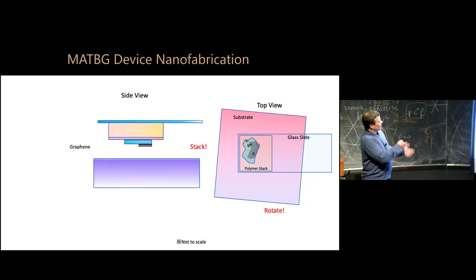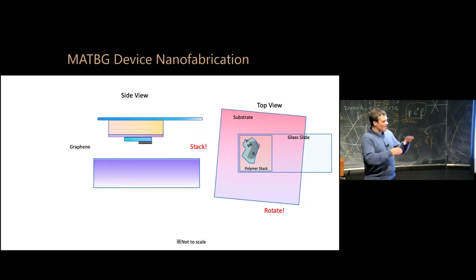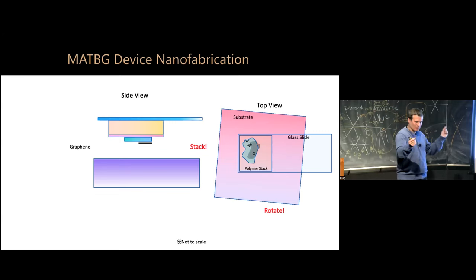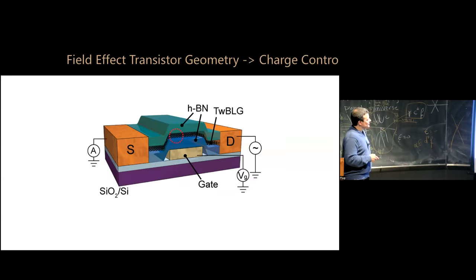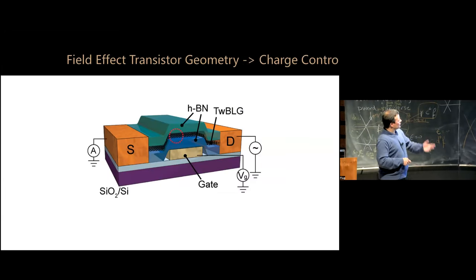And then you remove the two graphene sheets, and then we can do a lot of relatively complicated nanofabrication processing to make sure we can have electrodes attached to the tiny structure and measure the electronic properties. But it's very standard. Thousands of groups around the world do that type of nanofabrication. We end up with something which, for those of you with engineering background, is a field effect transistor geometry. We have the twisted bilayer graphene. We have hexagonal boron nitride on both sides, encapsulated on both sides. We can contact it with gold electrodes so that we can apply a voltage and measure a current.